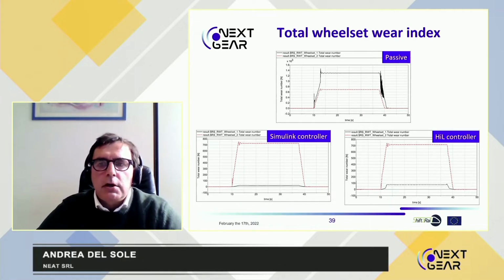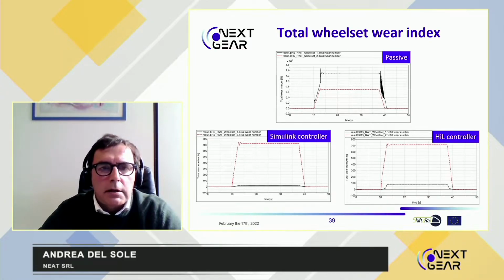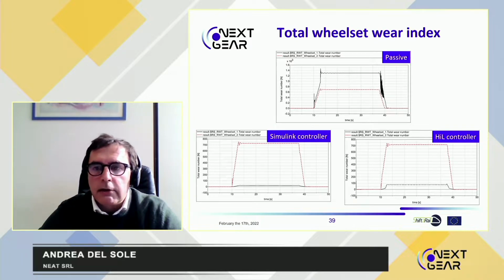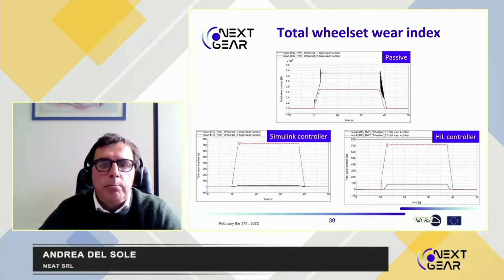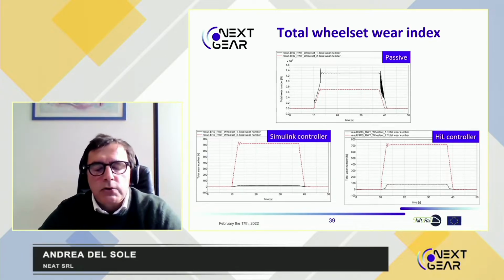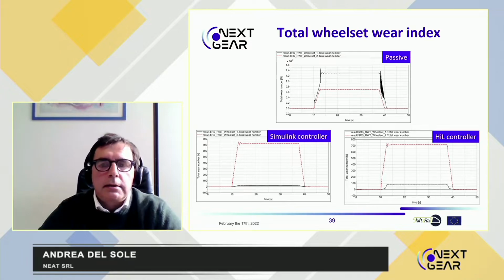This slide instead shows the results for the total wheel set wear index for the same 3 different simulations. The wear index of both wheel sets of the passive vehicle system is very, very high, especially the leading wheel set, identified as wheel set frame 1 in the graph. This phenomenon, together with the wheel set attack angle, reveals a very poor curving performance for the passive independent rotating wheel set system, which basically has no steering capacity. The wear of the controlled leading wheel set instead is significantly lower than the wear in the passive scenario, and the simulation shows that the wear index can be reduced by up to 94%.